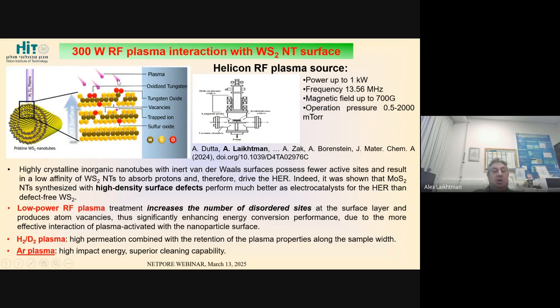As I have just told, there is some residual oxygen from the synthesis process. In addition, there is also absorption of water. Generally, it's possible to remove this water by annealing in a vacuum in the same plasma chamber at 150 to 200 degrees for half an hour to 1 hour. But for some reason, in several experiments, we did not do this. And it turned out that it's very beneficial to leave this small amount of water on the WS2 surface before performing the plasma treatment.